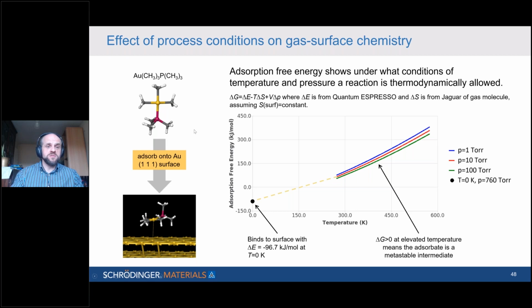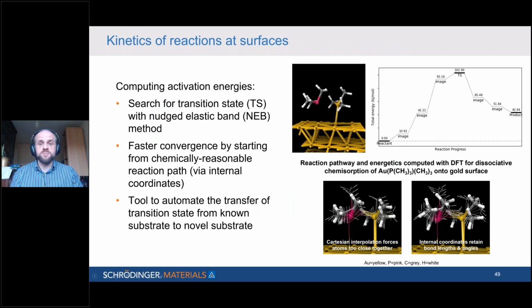Now, it can be tedious to work out the entropy of molecules and the effect of temperature and pressure. So again, we try to automate this into the software, and you can see the type of output that we get here. These lines show the way the free energy varies with temperature for 3 different pressures that are relevant for the process. And these 3 lines, they're all above 0. So that means that the free energy of adsorption is greater than 0, and it means the molecule doesn't have a long lifetime on the surface. It's going to adsorb but then desorb again. And this is actually quite typical of the reagents we see in these kinds of growth processes, that they hit the surface, but not all the reactions actually lead to growth, and the sticking coefficient is a lot less than 1.